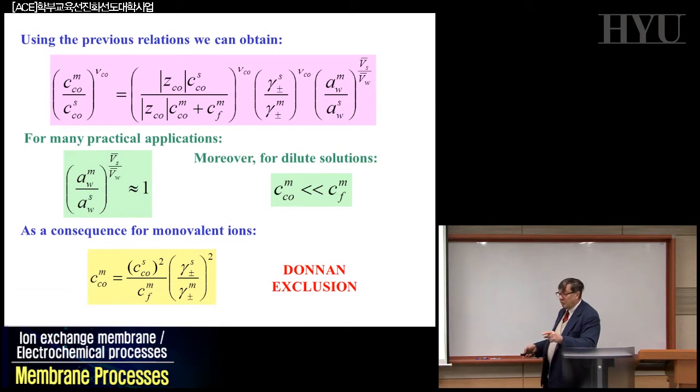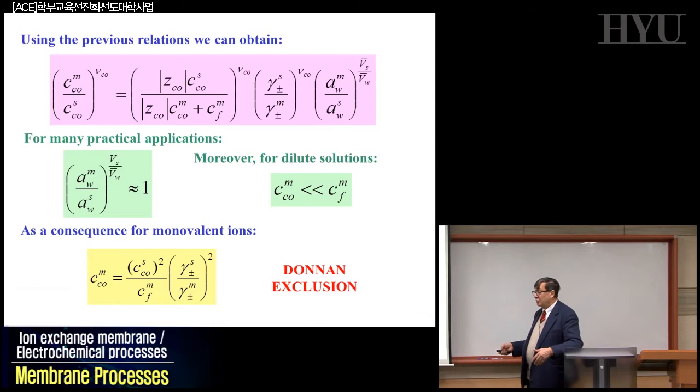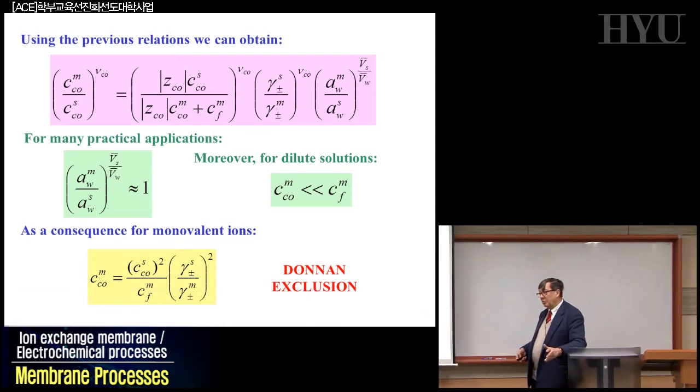That means that if we are working, as I told you last time and I like to repeat, with the new systems today, for example, if you want to produce energy using reverse electrodialysis, we'll see what we are talking about, we need a system where we concentrate the solution. Seawater is relatively dilute. We will work at 5 molar. If you want to work with a 5 molar solution, you need a very high fixed charge density in your polymers. Otherwise, this effect will not be significant.